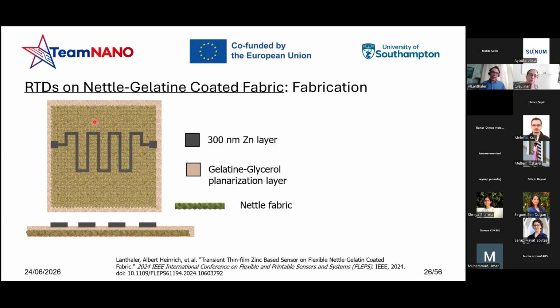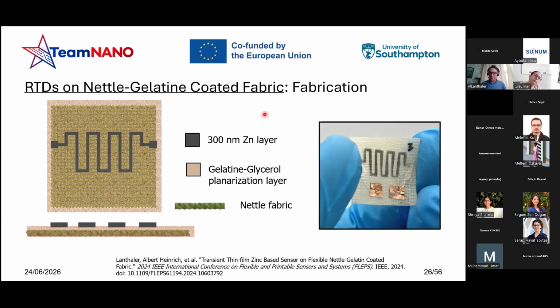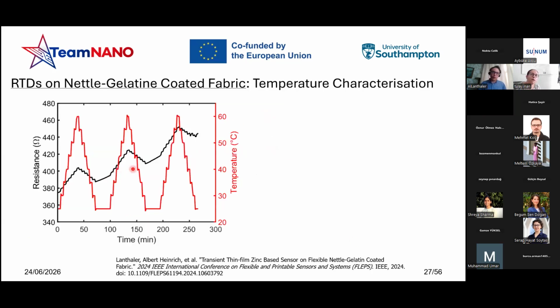And after that, I placed it into vacuum conditions, coated with the same vinyl tape mask I mentioned before, and deposited a 300 nanometer zinc layer. And this is the final result. Was it working? Yes, it was working.